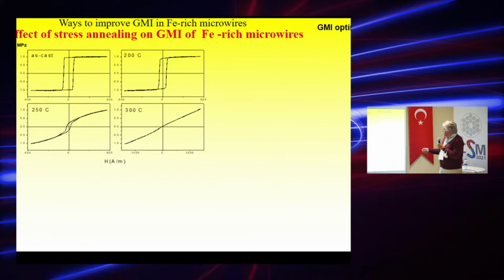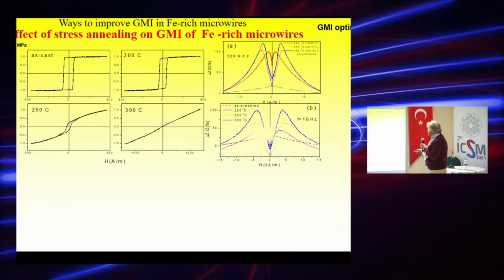For example, this is the same stress applied during annealing, and we change the temperature, and we can vary the hysteresis loop from this one to almost linear. So there is a lot of possibility to tune the hysteresis loop of that material. And of course, the GMI effect we improved still further, because you can see the difference is almost 1 order of magnitude in the maximum value of the magnetic impedance ratio from this one to this one.